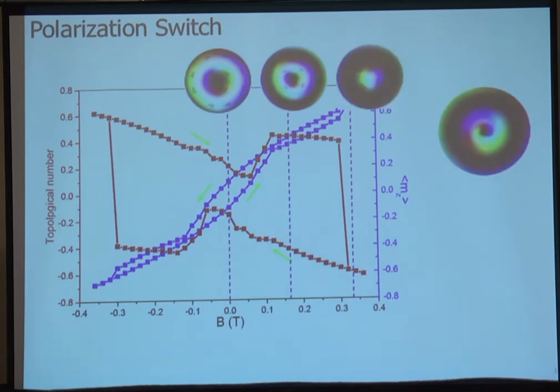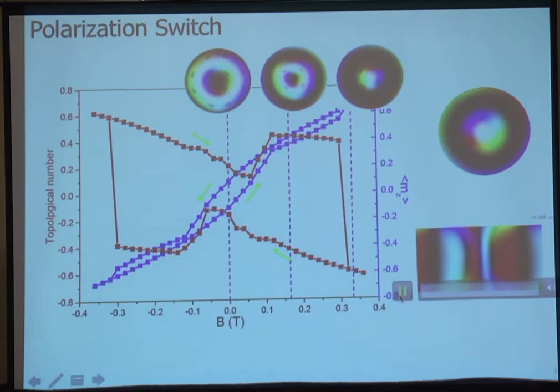So this is the dynamical process. You see the center skyrmion gets smaller and smaller, and in the end the central core collapses, because the central core tends to be anti-parallel with the external field. Actually, this polarization switch is accompanied by the emergence of Bloch points. You see, as time goes by, this is the side view. So you see that the center gets narrower and narrower, and then all of a sudden, a pair of Bloch points will emerge. And these two Bloch points propagate in opposite directions, pushed to the surfaces, and we realize this switch.